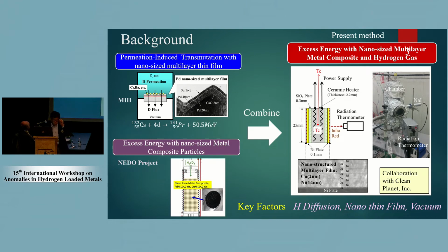Here's the background. I have been working a very long time in this field. When I was a researcher of Mitsubishi Heavy Industry, I engaged in the experiment of transmutation. We used a palladium and calcium oxide multilayer thin film with deuterium gas. We put cesium and made a permeation flow through the palladium multilayer, and we observed cesium to praseodymium transmutation reactions.